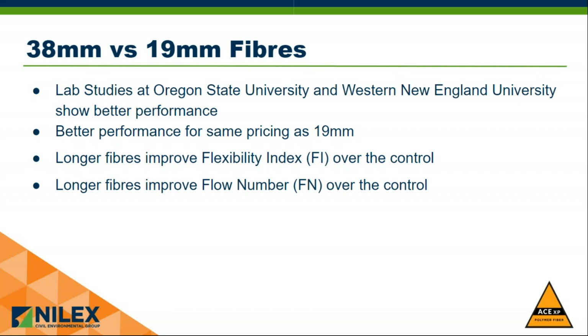Flow number testing also shows a 37% increase over control mixtures, suggesting that the longer fibers improve rutting resistance of the asphalt. The 19 millimeter fibers also showed this increase, but it was only a 30% increase, not a 37% increase. So hence a slight performance increase over the shorter fiber, but for no impact on the cost. It makes a lot of sense to go with the longer fibers.